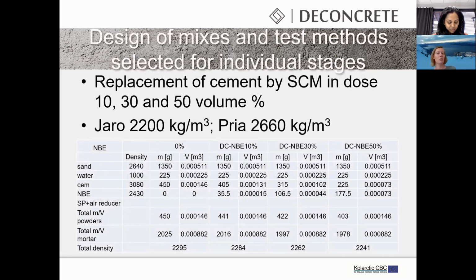Design of the mixes. For this presentation, I selected the part with testing of the mortar. The mix was designed as a replacement of cement by 10, 30, and 50% by volume, with cement replaced by the supplementary cementitious materials. There were differences in the particle density of the input materials, and that's why we didn't replace by weight, but by volume percentage.